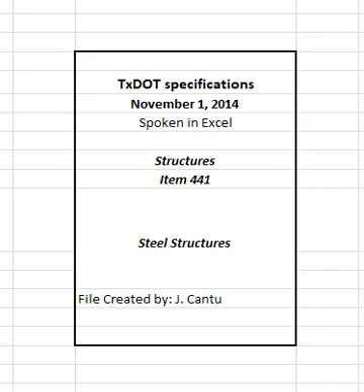3.2.5.1 Radiographic testing. Radiographs must have a density of at least 2.5 and no more than 3.5, as a radiographer confirms. The density in any single radiograph showing a continuous area of constant thickness must not vary in this area by more than 0.5. Use only ASTM System Class 1 radiographic film as described in ASTM E1815. Use low-stress stencils to make radiograph location identification marks on the steel.